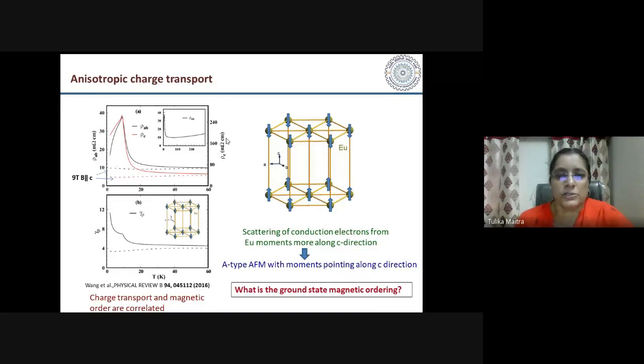But because this Eu absorbs neutrons, it was not possible to determine the exact magnetic ground state for this compound. Okay, so one proposal was made from the charge transport measurements. When you look at the charge transport measurement in this compound, what we see is that the charge transport depends on the magnetic order. Okay, this charge transport and magnetic order are correlated.